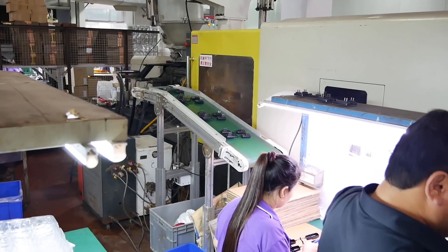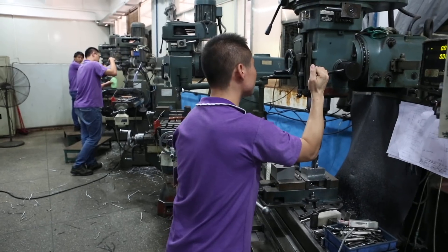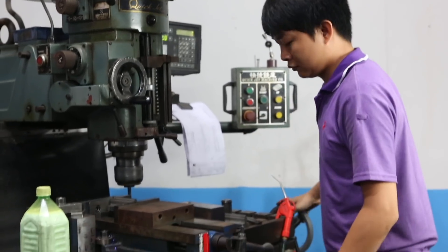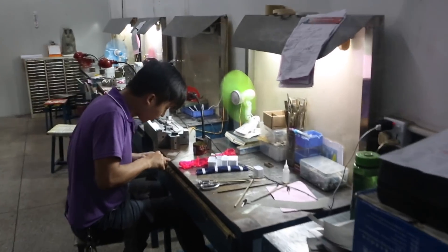Going to the factory showed us why tooling is an expensive process — it's tedious, very intensive, and there's a lot of checking that needs to be done. For a short run, it's common to use a silicone mould, which can do a dozen parts before you need a new one. At the other end, you have 3D printed or CNC machined parts for small quantities. But if you're going to make more than a few thousand of something, you probably want to tool it. Typically they'll use aluminium or mild steel for medium production runs and very hard tool steel for large runs, getting anywhere from 100,000 to 10 million parts out of a tool. Cost effectiveness — you can't beat injection moulding.